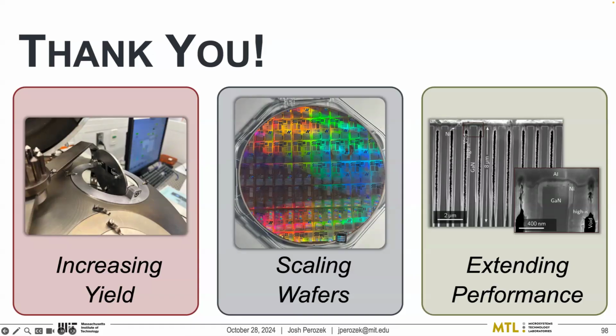No, so that's a good point there. Anytime that you have any very high aspect ratio features, it becomes hard to just get stuff down into the bottom of them. These trenches are, in this case, 8 microns deep, but only 400 nanometers wide. Just etching down into there becomes very challenging. The ions can kind of stray off to the side and hit the sidewall instead of the bottom where you want that to happen. And you notice that the etching rate decreases as you go deeper. So eventually you're going to have to make the opening a little bit wider if you want to go deeper.